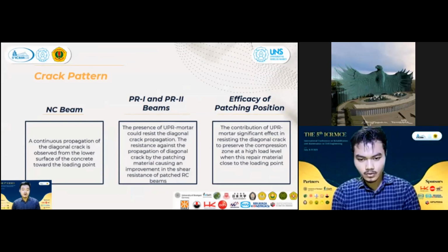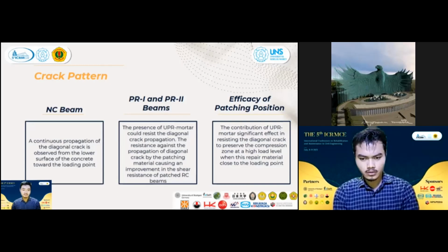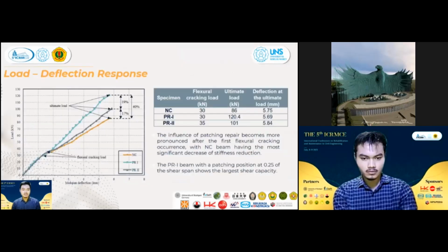And then for efficacy of patching position, the contribution of UPR mortar has a significant effect in resisting the diagonal crack to preserve the compression zone at a high load level when the repair material is close to the loading point. Next, load deflection response. You can watch it on this chart.